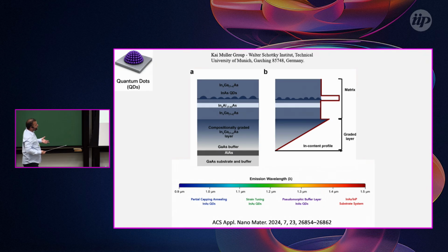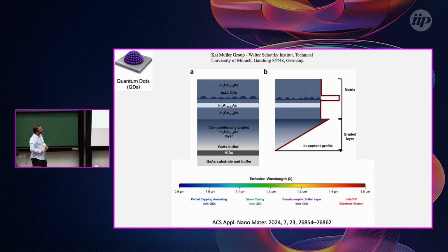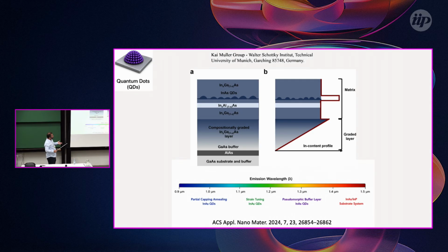Another kind of method, which basically two groups are doing, is the group of Kai Müller and Peter Michler. It's about this pseudomorphic buffer layer. Basically, they start with an indium gallium arsenide layer with around 20% indium content, and they grow until, let's say, 36%. After this, they decrease the percentage, and they grow these indium arsenide quantum dots on top of this buffer layer. And with this, they managed to reach, let's say, 1.3 or 1.5 microns for the quantum dot emission. Another way you can do it is growing not on gallium arsenide substrates, but on indium phosphide substrates. With this, you can also engineer the emission of these quantum dots.